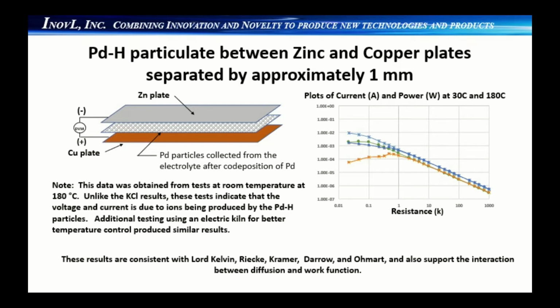Two thin strips of Teflon, approximately 1 millimeter thick, were positioned at each end of the copper sheet, and the zinc plate was placed on top. A load test was conducted at room temperature, and another load test was conducted when the cell, placed in a barbecue, was heated to 180 degrees C. The data from both tests are plotted, and unlike the test with potassium chloride, the cell voltage and current did not substantially change at the higher temperatures.